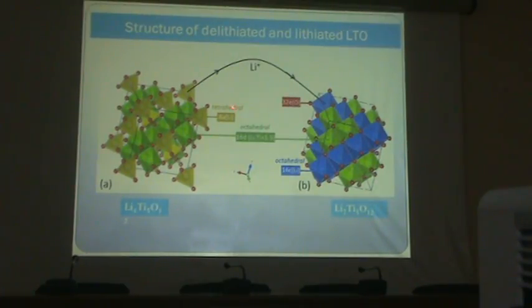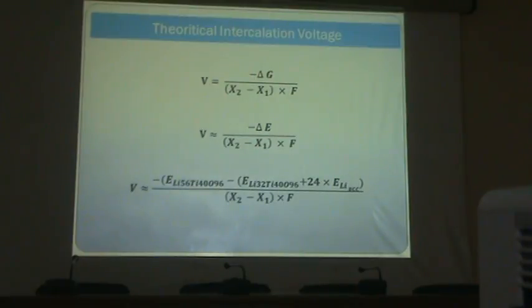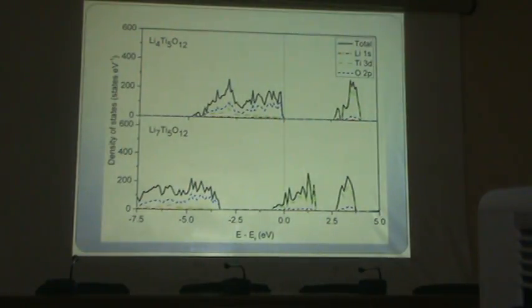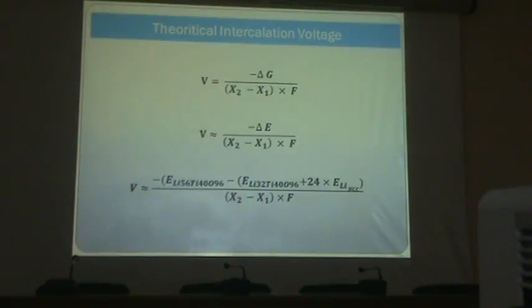So this spinel structure changes to a cubic structure. In this structure, the lithium goes from the tetrahedral 8a sites to the 16c sites and sits there. Using this structure, we calculated the theoretical voltage, and it came out around 1.6. This was a first attempt, playing around with this.